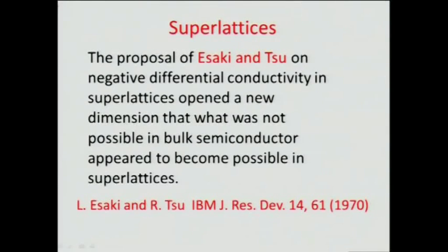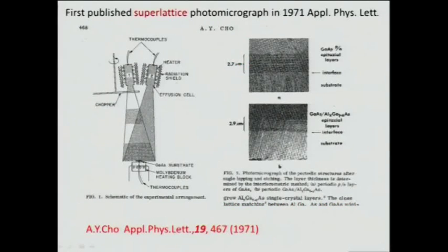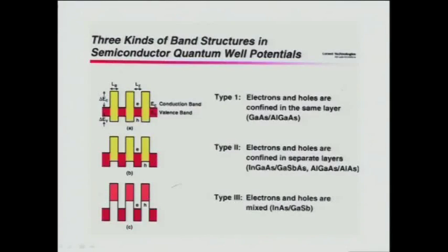That here shows the superlattice first proposed by Esaki and Tsu. The negative differential conductivity in the superlattice opened a new dimension: what was not possible in bulk semiconductor appeared to become possible in superlattice. We then quickly tried to demonstrate that MBE can make these superlattice structures. In 1971, I published the first paper on the demonstration of MBE growth of superlattice structures.